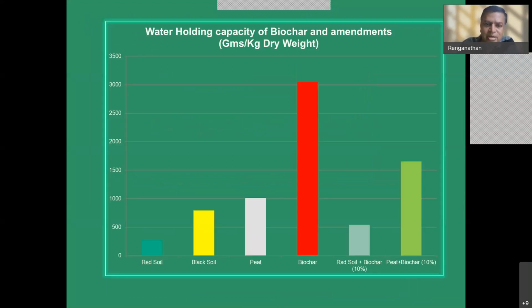These are experimental data. The water holding capacity has gone up tremendously compared to red soil, black soil, peat soil. Red soil plus biochar has increased water holding capacity, and the same is the case with 10% biochar with peat soils. So a small addition of biochar to the soil will increase the water holding capacity. In a matter of about 3 to 5 years, soil holding capacity can go up, or the water requirement can come down by something like 50 to 30%.